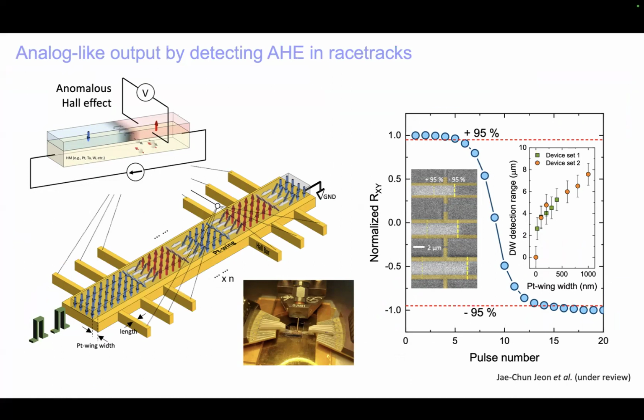sub 100 nanometers. And so to do that, on the left-hand side, you can see a cartoon to scale of the magnetic racetrack, a simple ferromagnetic racetrack on a platinum layer which we use to create spin currents. And we build a wing. I don't know if you can see this. The platinum layer is designed to be slightly wider than the magnetic layer.